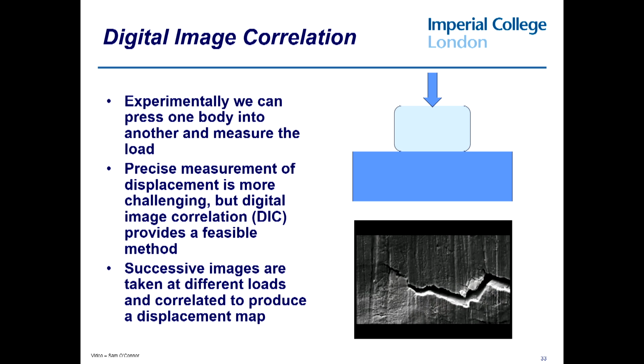And what you can do by digital image correlation is you can take each of those images in the video and you can overlay them, and you can match up part of image 1 with image 2, and you can find out the displacement. You can get a complete displacement map. And that's really useful. We can use it in contacts.